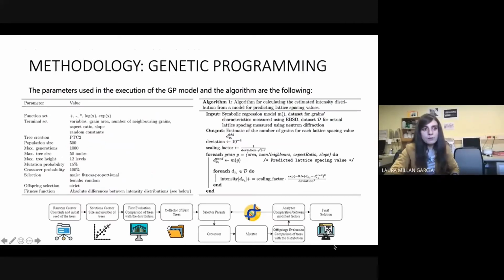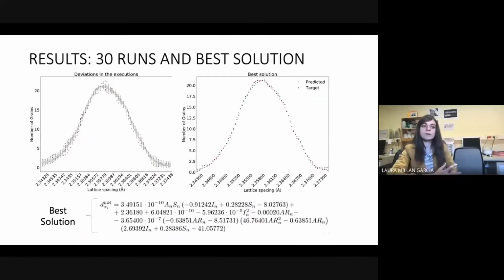We introduce the following parameters and the algorithm in the HeuristicLab software. The steps in the analysis are shown in the script. 30 executions were made. The best solution was chosen considering the minimal error between the target and the predicted peak. An expression for the lattice spacing is extracted from the predicted peak, and the variables are the four microstructure factors: area, aspect ratio, number of neighbors, and slope.